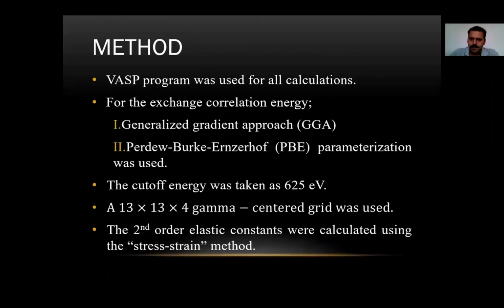Approaches that take into account the spatial variation of density are called generalized gradient approximations. GGA has been shown to better predict bond length, and total energy for many systems. Due to the large density gradients in some materials, the GGA approach is used instead of LDA. Density functional theory reduces the Schrödinger equation written for the n-electron systems to the n-single electron Schrödinger equation. The most important problem in the DFT is that exchange correlation energy is not known.